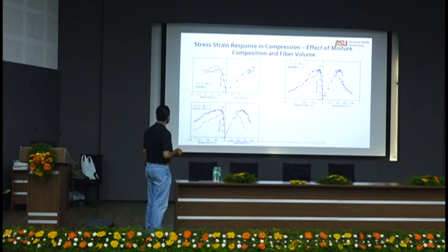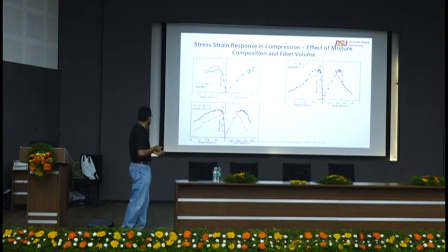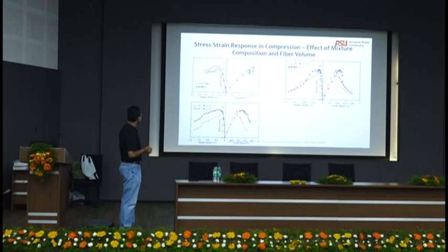And then look at the axial and radial strain. All these tests were done with radial strain control, so you can get very nice strain descriptions. You get a maximum radial strain at about 60-70% stress of about 0.3%. Very good radial strength.